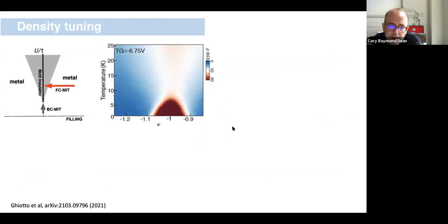So here I'm plotting, in a device, I think this is the 4.2 degree twist device, just a focused temperature-density filling dependence here. So here, filling 1 corresponds to half filling, or this has become, I think, a better nomenclature. Filling 1 corresponds to exactly 1 hole per Moiré unit cell. And at this point, I have this Mott gap that we observe.